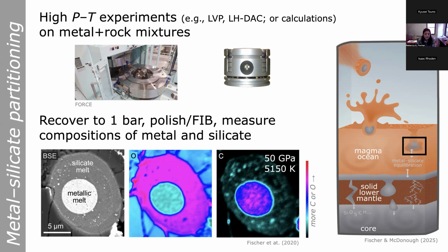And then we recover the samples to 1 bar. We polish or extract a piece of the sample using a focused ion beam. So we expose the hot part in the center where the reaction took place. And then you can use various different analytical techniques to measure the compositions of the metal and silicate that reacted.